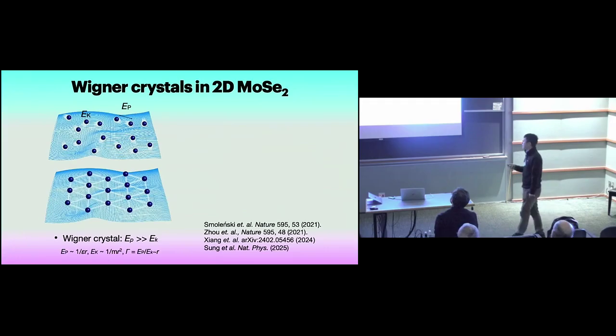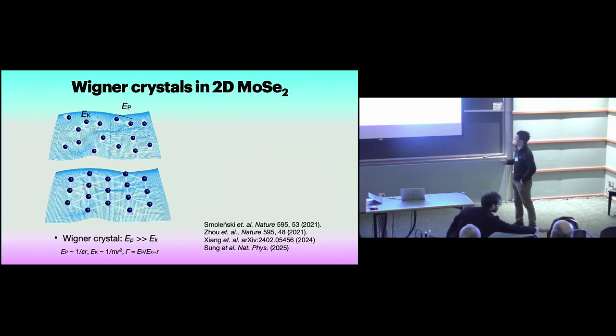If we look at the scaling of the potential energy and the kinetic energy, we realize that this Wigner crystal is most stable at a low density, where the interparticle distance r is very large, right? That's when the kinetic energy is small, so the potential energy dominates over it. This typically happens at very low density and very low temperatures. Historically, the Wigner crystal has been very difficult to realize because the kinetic energy always dominates at densities comparable to the defect density.